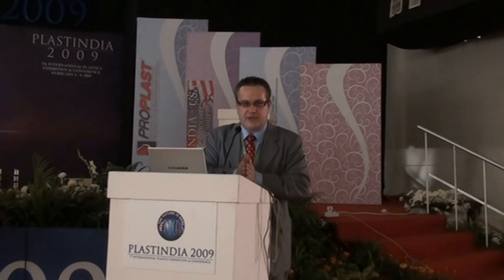The mould can be made using various mould making techniques. If it's a relatively small mould, then we can use either laser sintering or selective laser melting, or even metal spraying to make the mould. But when we're talking about large tools, then we use conventional CNC machining techniques, splitting the mould cavity into 2 parts, machining both sides and then bringing it back together.